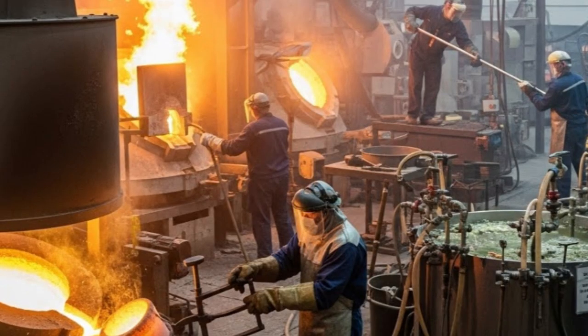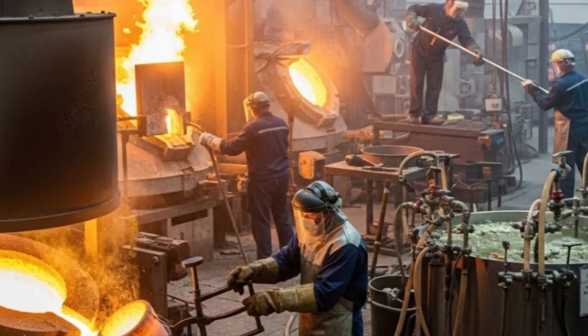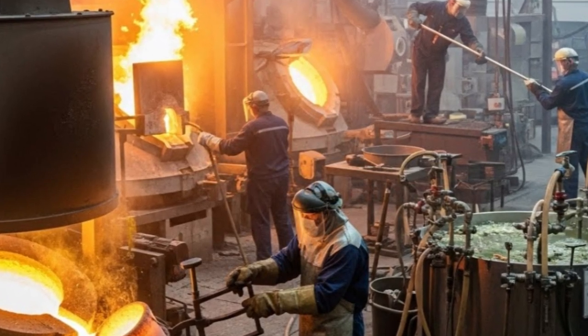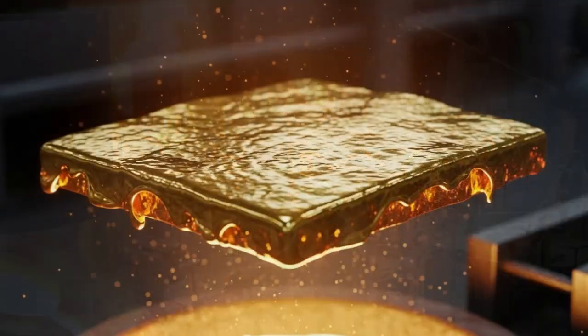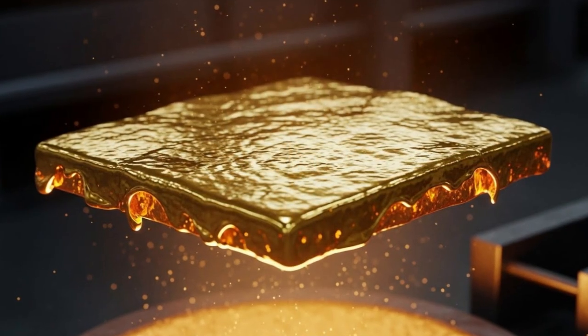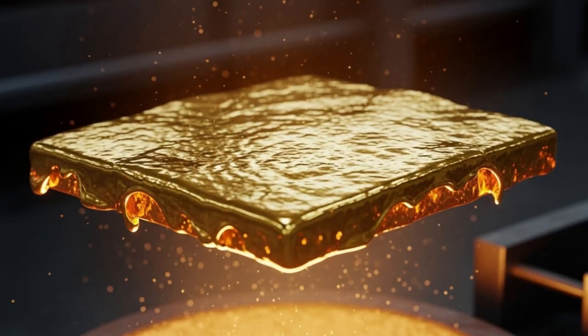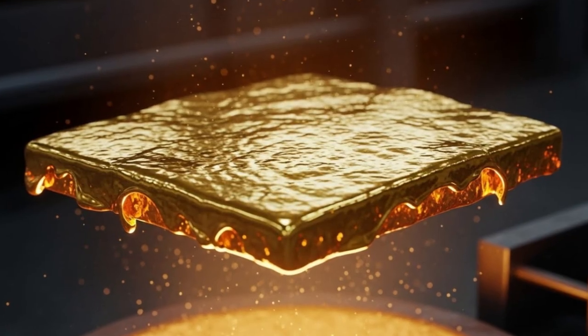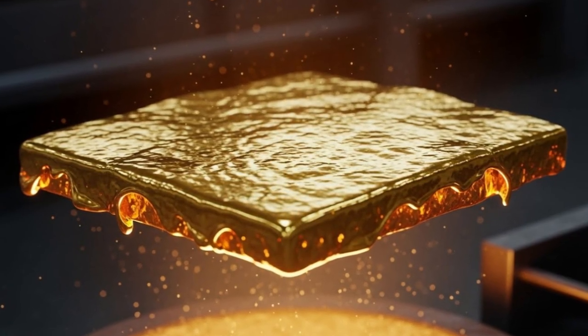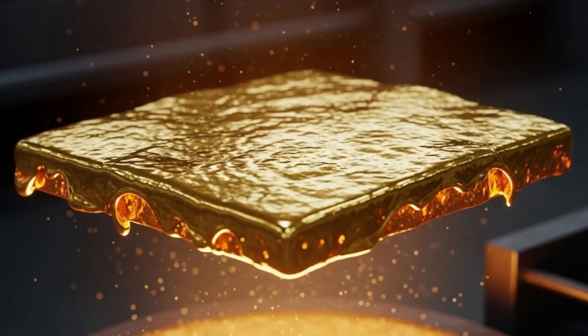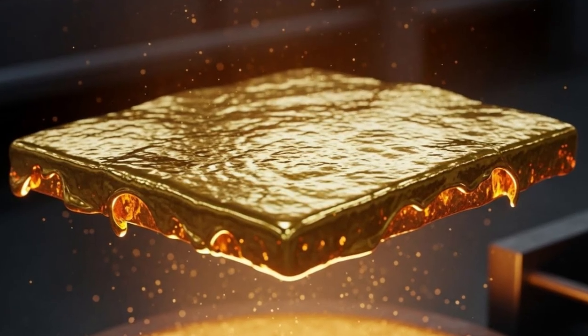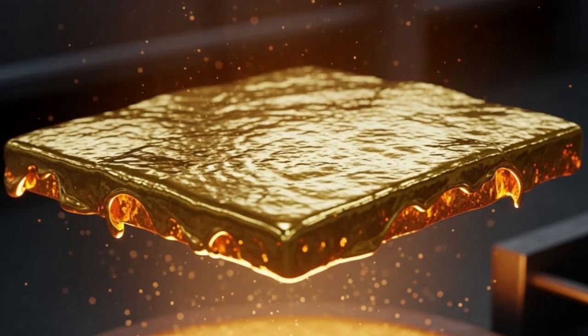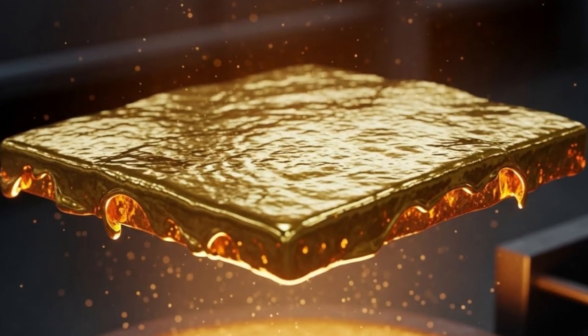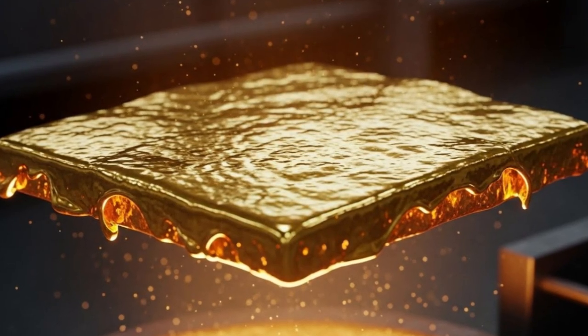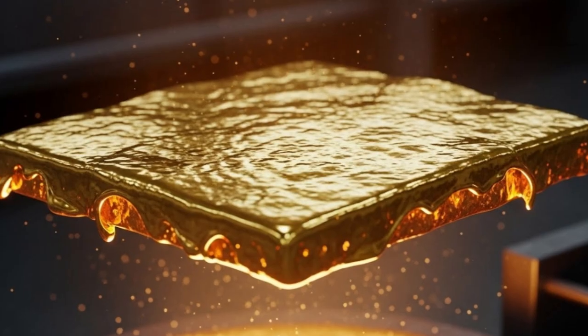Inside the furnace, temperatures rapidly rise beyond 1,064 degrees Celsius, exceeding gold's melting point. As the heat increases, the solid concentrate liquefies, transforming into a glowing pool of molten metal. At this stage, technicians add carefully measured flux compounds. These materials are designed to react with unwanted elements, such as iron, silica, and other residual metals, binding them together.